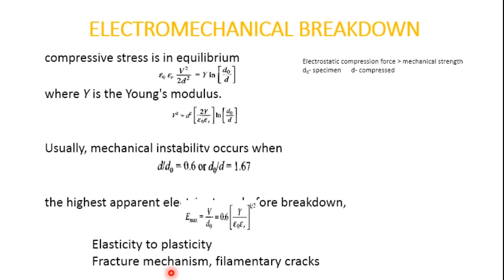Recently this theory has been modified based on the concept of fracture mechanics. The new mechanism considers that filamentary-shaped cracks propagate through the dielectric material, with both electrostatic and electromechanical strain energy stored due to the applied electric field — similar to conventional mechanical crack propagation in brittle materials. These cracks propagate spontaneously if the strain energy release rate is greater than that required to overcome the toughness of the material. These filamentary cracks are responsible for conduction and breakdown in electromechanical breakdown.